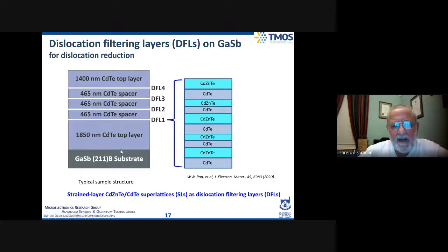The idea is that if you get a defect propagating from the substrate because of lattice stress from the cadmium telluride/gallium antimonide interface, that defect structure, which is a threading dislocation, can either terminate or perhaps be deflected by these dislocation filtering layers and not reach the top layer, because it is the top semiconductor layer where you fabricate your device, and that's the crucial layer from a device performance point of view, not down here.